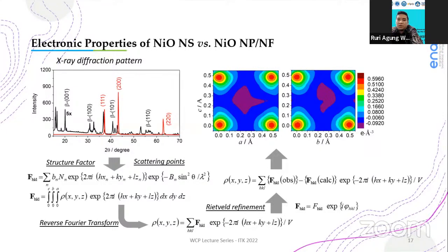from the structure factor, or F here, which is a factor with magnitude and phase from all scattering points of all the observed diffraction planes within the unit cells. And then the phase can be estimated or calculated from the Rietveld refinement. So then the charge density can be obtained and also visualized from the inverse Fourier transform and presented in 2D maps or 3D maps. But here I only use 2D maps to show the distributions of charge density within the unit cells.